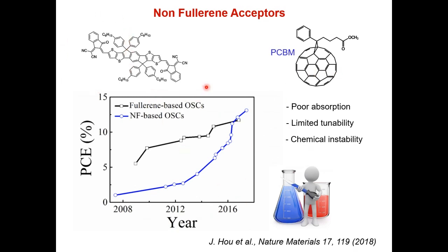So recently, a new generation of acceptors has appeared. They look like that. These are small molecules. And starting from 2016, they have started to behave very well, much better than C60. Very recently, we are reaching PCE, power conversion efficiency, of about 18%, which is a fantastic number for an organic technology with all the advantages of processing. This is really a revival of the field, and now there is a new boost to understand those materials and to make organic devices with very high efficiency, maybe not competing directly with silicon, but that you can exploit in many applications where you want to play with flexibility, and we'll see that in the following.